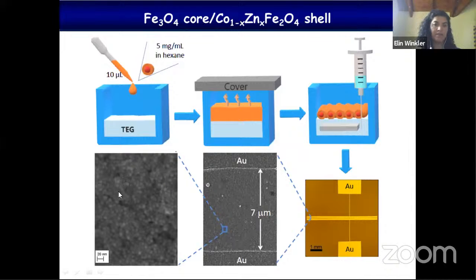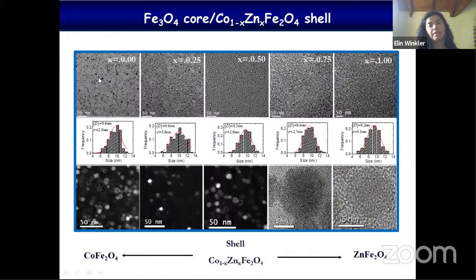This region is shown with a large magnification, and we measure the conduction across this direction. So, these are all our systems. These are the core shell systems, where, remember, the core is always magnetite and we change the shell. In this case, the shell is cobalt ferrite, and then we replace cobalt by zinc until we have zinc iron ferrite. And here you can observe some core shell structure.